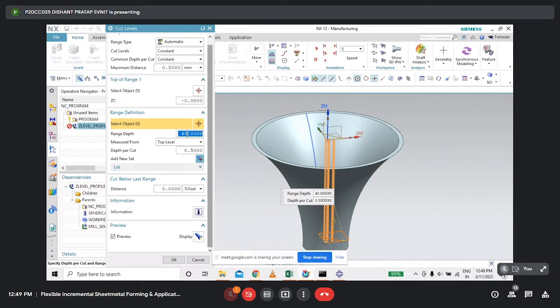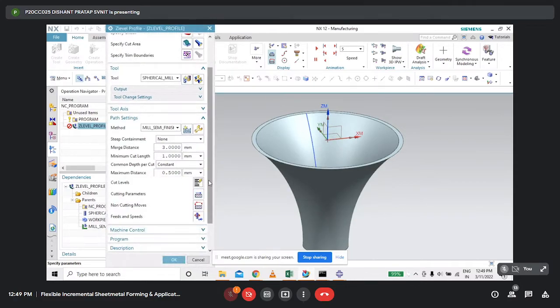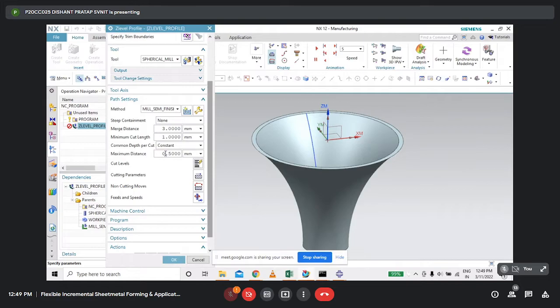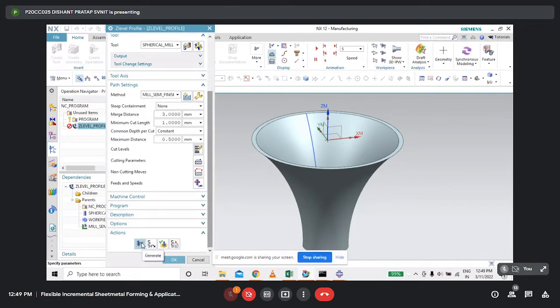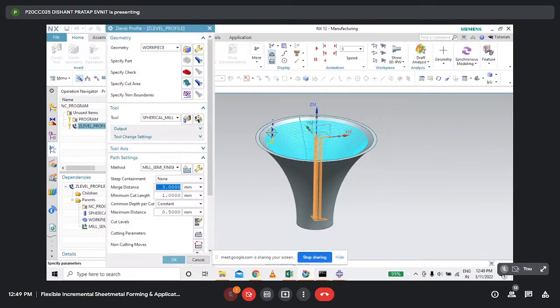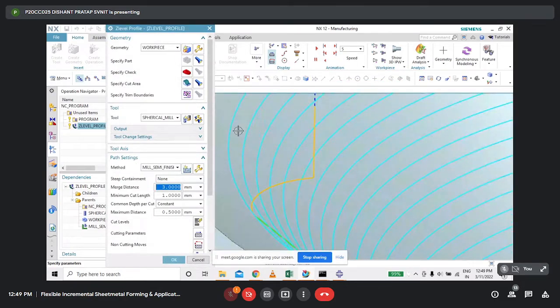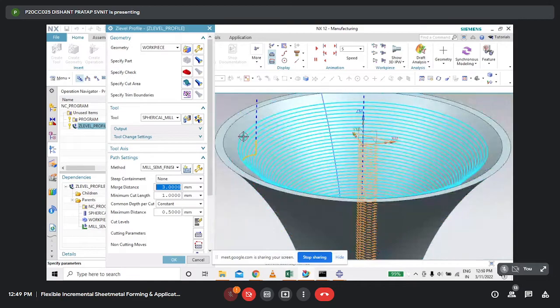I have given the depth because I have decided that my conical frustum will be of 40 mm depth. So I have given the range depth of 40 mm, and I also decided that it should start from there only. Then this is my maximum distance, the depth per cut, also known as step depth. So the distance between two contours of the tool path will be 0.5 mm. I would like to show you. The distance between these two contours will be 0.5 mm. We can vary this, but for my project work I have kept it at 0.5 mm.